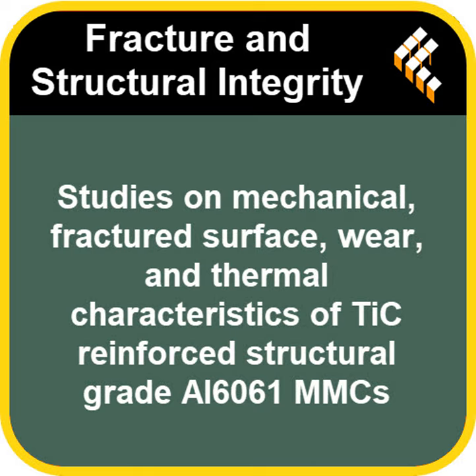Exactly. And the research showed that the tensile strength of these new composites increased by an impressive 18.47%. It's a significant jump. And this efficient load transfer is facilitated by chemical bonding and also mechanical interlocking at the interfaces. Where the particles meet the matrix, that's what makes the material so much stronger. Okay, almost a fifth stronger just from this additive. That's a massive leap for design engineers.